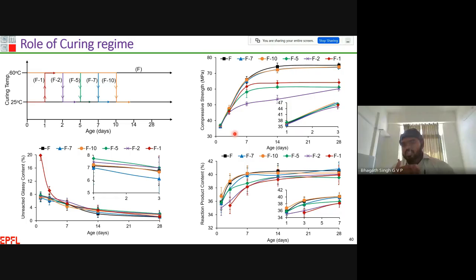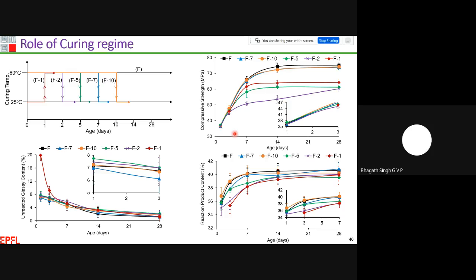If you want to use it for precast applications, how much time do we have to cure at the elevated temperature? If you are able to use pure fly ash and optimize the mix proportion, curing for 7 days is more than sufficient to achieve the maximum compressive strength in your system. I cured for 7 days, followed by the reaction progressing over the remaining days, and I achieved about 72 megapascals compressive strength in our system.